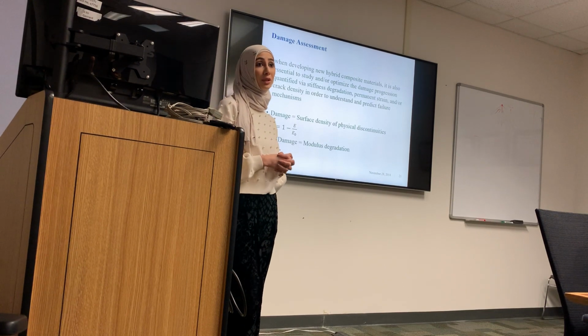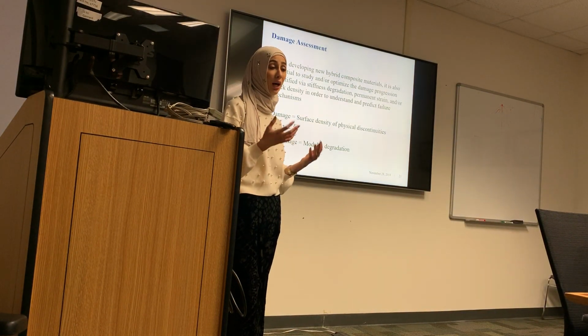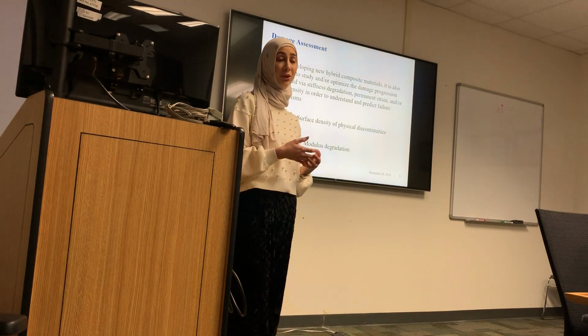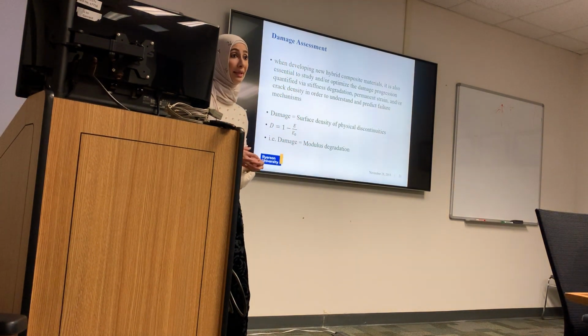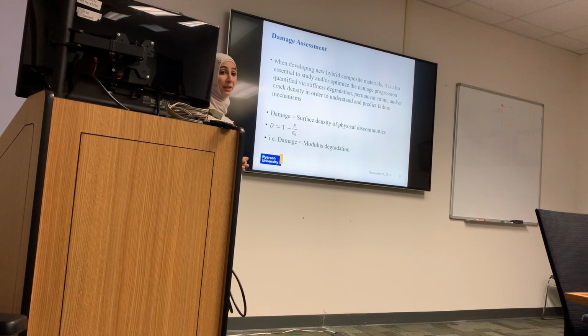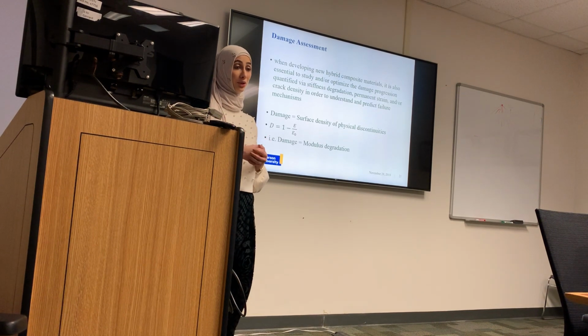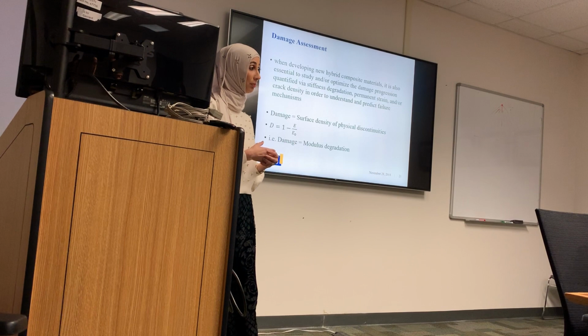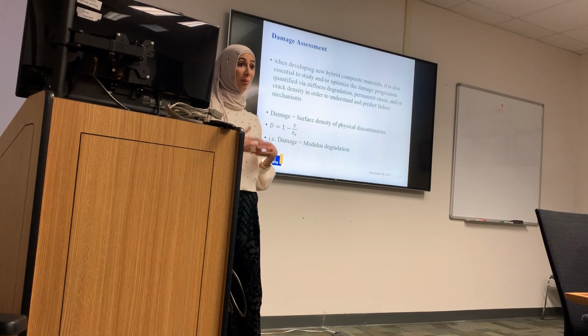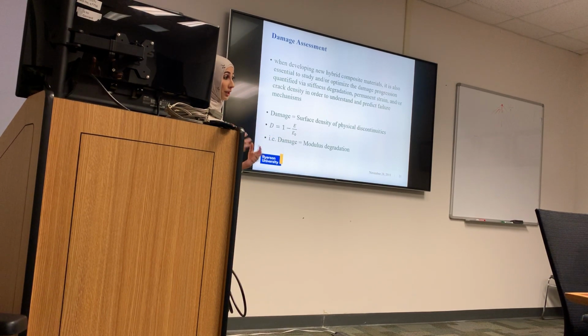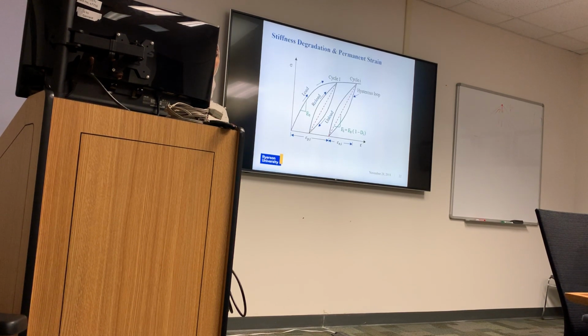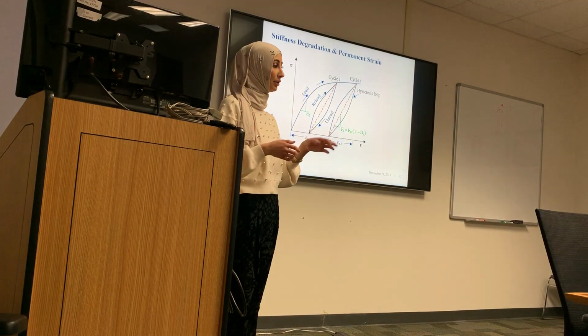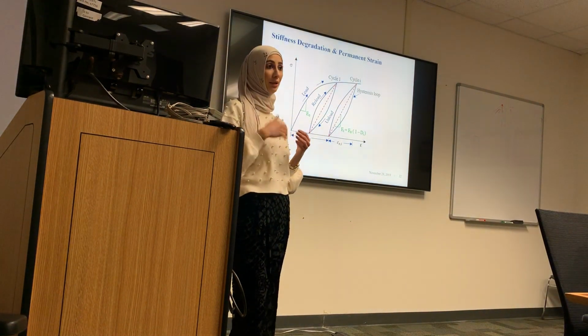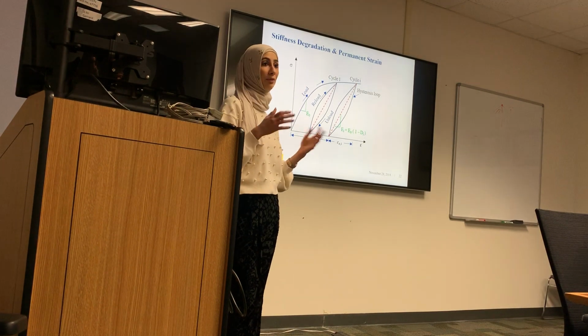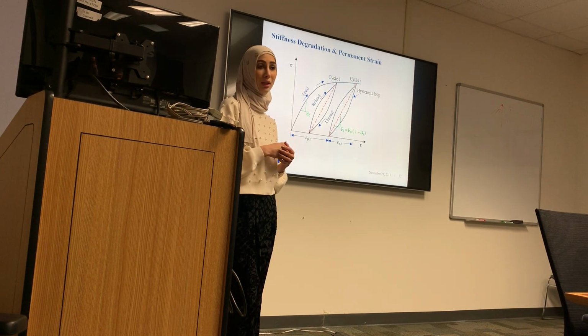When introducing a new material, it's very important to study the damage evolution, so how the material reacts with the presence of damage. Based on the classical damage model, damage is defined as a surface density of physical discontinuity. The damage parameter D was determined based on the reduction of the modulus. So what we did, we took each specimen and loaded and unloaded it for 5 to 7 levels of stress based on the ultimate stress.